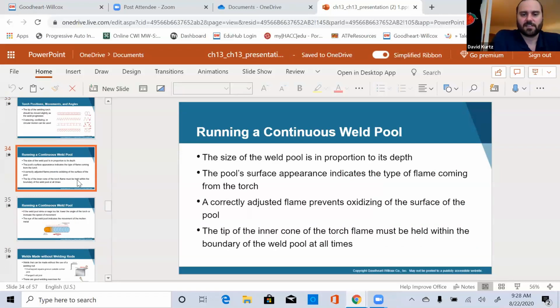Running a continuous weld pool, the size of the weld pool is in proportion to its depth. The pool surface appearance indicates the type of flame coming from the torch. A correctly adjusted flame prevents oxidizing of the surface of the pool. Oxidizing would be burning it up, or melting too fast. It's not creating a good weld puddle, and your weld bead is going to be affected. The tip of the inner cone of the torch must be held within the boundary of the weld pool at all times. So your flame is going to be very close to your puddle. You're going to need that heat there the whole time, so we want to keep it close, within a 1/4 inch to 3/8 of an inch away from our weld pool.